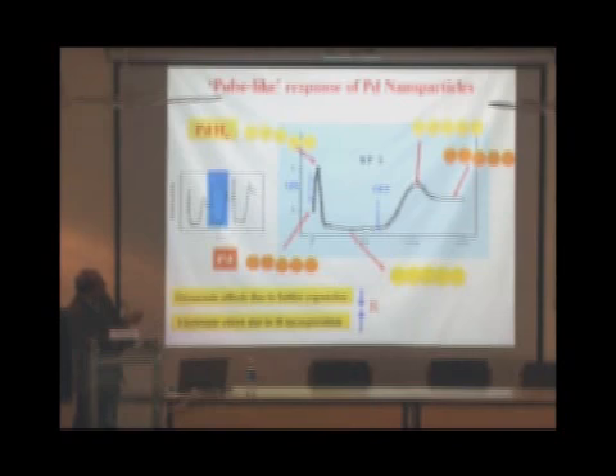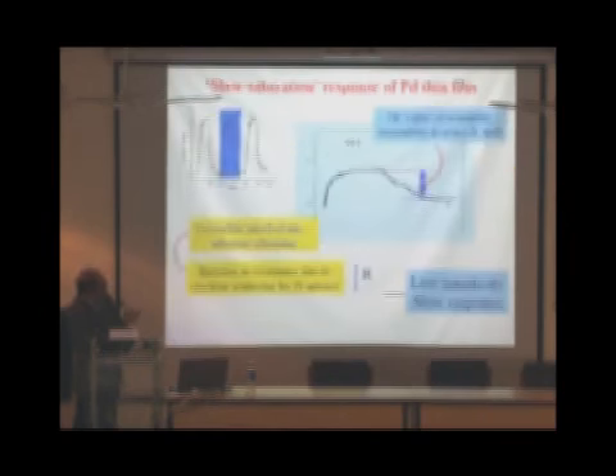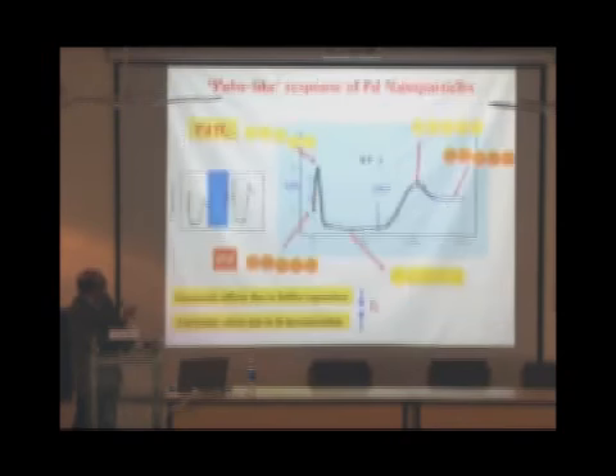In place of the slow saturation effect, the moment we put hydrogen at this point, the electrical resistance goes up, and then it comes down by itself, even though the sensor is still exposed to hydrogen. At this point, we remove the hydrogen, the resistance goes up and it comes back to the same point. So in place of the resistance just increasing and saturating, in the second case, the resistance goes up and comes down. This is called a pulse-like response.